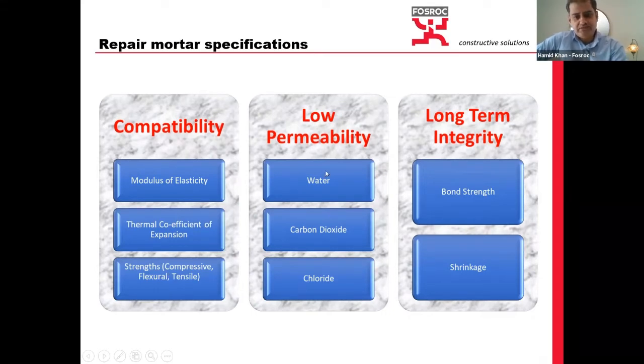For low permeability, we should look at the repair mortars, which should comply with EN 13295, the EN standard for carbon dioxide diffusion resistance. Chloride as per NT Build 443. So the repair mortars should comply to those standards as well. And obviously low permeability against moisture and water. And when we talk about long-term integrity of these repair mortars, that means they should have low shrinkage.